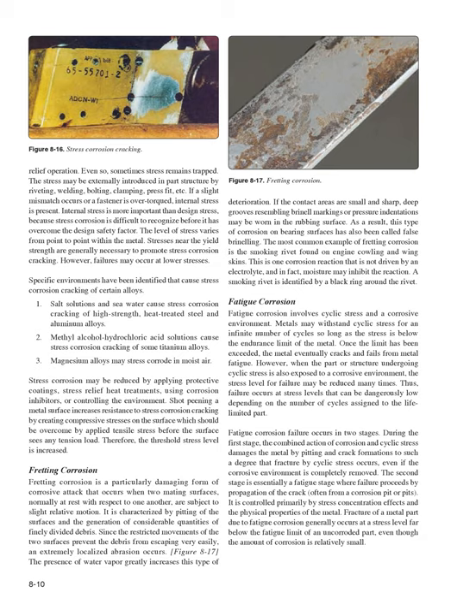Internal stress is more important than design stress, because stress corrosion is difficult to recognize before it has overcome the design safety factor. The level of stress varies from point to point within the metal. Stresses near the yield strength are generally necessary to promote stress corrosion cracking. However, failures may occur at lower stresses. Specific environments have been identified that cause stress corrosion cracking of certain alloys. 1. Salt solutions and seawater cause stress corrosion cracking of high-strength, heat-treated steel and aluminum alloys. 2. Methyl alcohol hydrochloric acid solutions cause stress corrosion cracking of some titanium alloys. 3. Magnesium alloys may stress corrode in moist air.